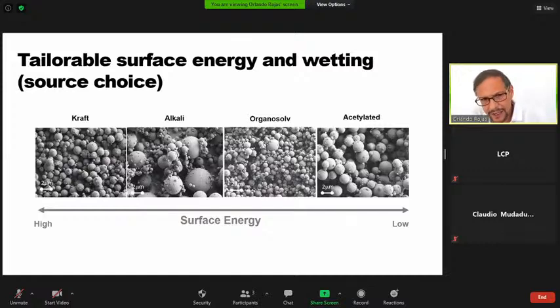And one beautiful aspect of these particles that I always mention in my talks is that here we have a beautiful knob where we can control the surface energy, wettability, and in general, the chemistry and properties, including thermal properties of these lignin particles. And this is depending on the processing that we use to obtain the lignin. We can change, for instance, the surface energy from being very high on the far left to being very low on the far right. So more wettable to less wettable.